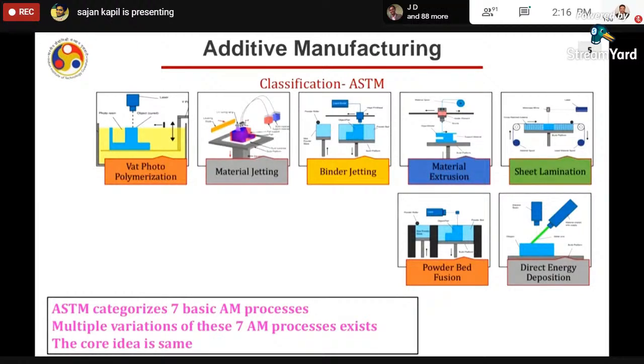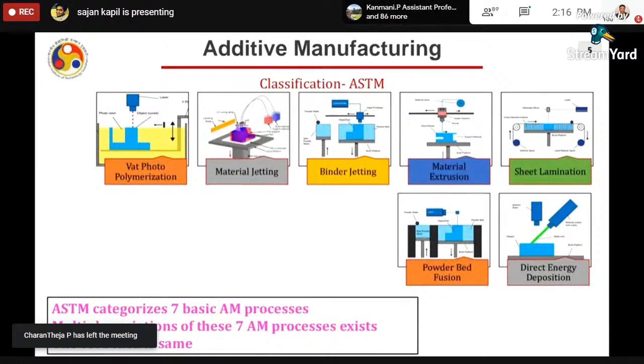In direct energy deposition, we usually do not have anything on the substrate, and the powder or wire or sheet, or in the form of strip maybe, are fed into the molten pool, and that molten pool is created by some energy source like electron beam, laser, or a conventional welding process like TIG, plasma, or MIG. So these are 7 basic AM processes. There are different variants, but the core idea is same. All these processes build a part in a layer by layer manner.